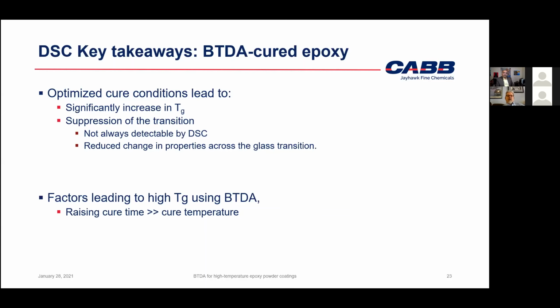Yes. And the practical part of that, and this is important from a commercial standpoint, the coating's good, it's put on, but it meets its final performance after a few hours in service, and that's not unprecedented. We're not asking people to tell your customer to cure the powder at 24 hours at 200 C. That would be very impractical. So yes, that's an excellent point. That brings the coating to a functional level of cure so that the part can be handled and put into service, but then it will cure further before the full force of the service environment takes place.